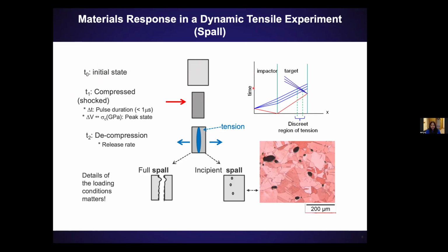And if you were looking in the time space diagram, this x-axis is along your sample and time is just time. At zero time, there's nothing going on. When you get impact on the sample, you generate a shock wave in your target. You generate a shock wave in your impactor. These waves get to the free surface and get reflected back as a release wave. Essentially, what they're doing is trying to bring your target down to zero stress.